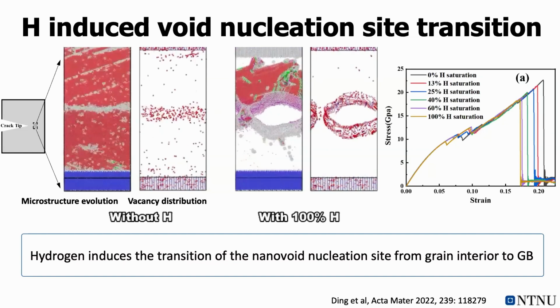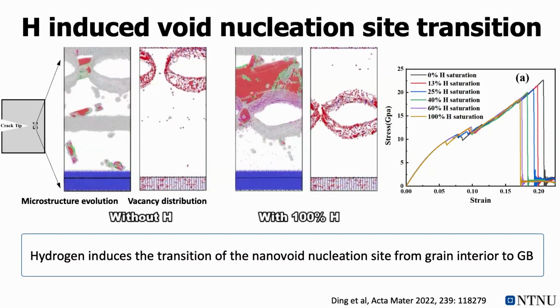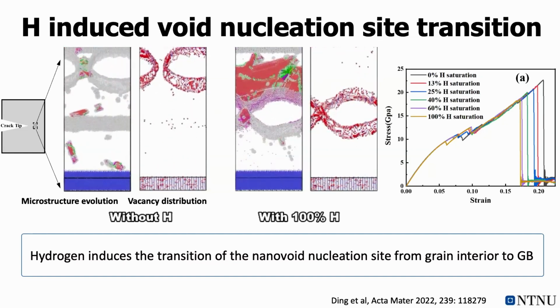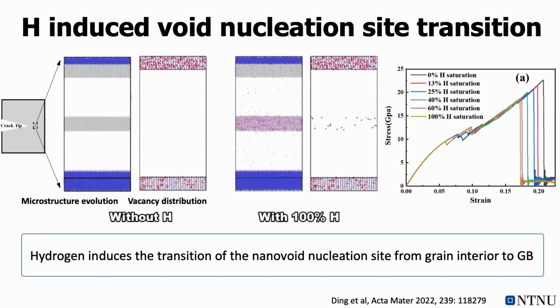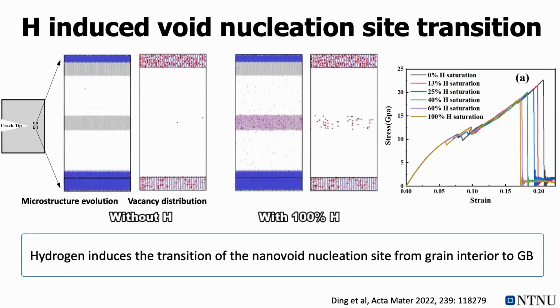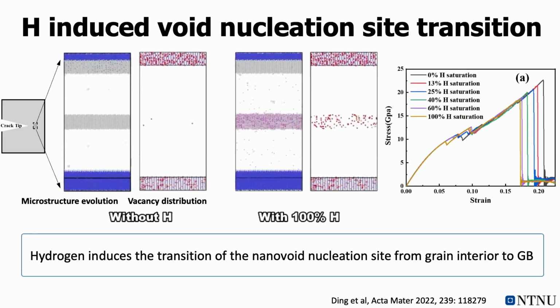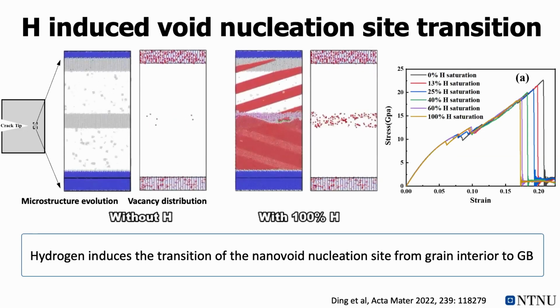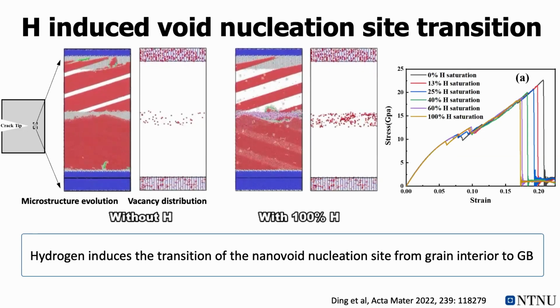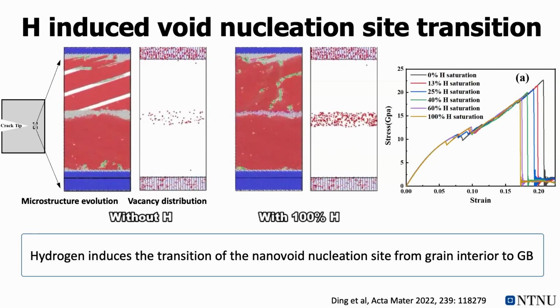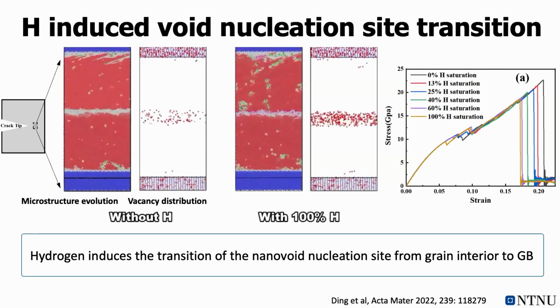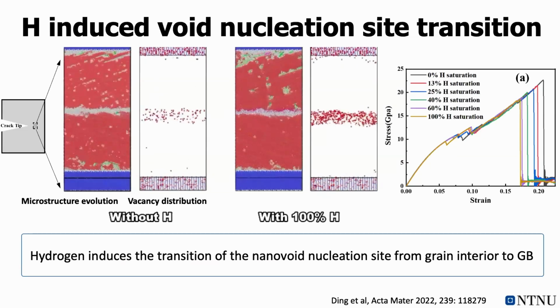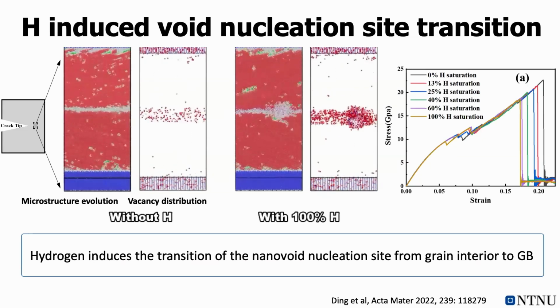It's around 2 times CTOD in front of the crack, so it's a really high stress area. Then we do the uniaxial straining test of this bicrystal material. What we can compare here is without hydrogen and with hydrogen. Of course, we see a lot of hydrogen trapping in the grain boundary area here.